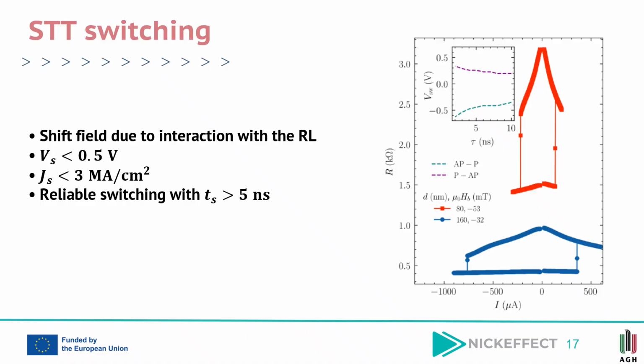In addition, reliable switching operation was achieved for pulse widths longer than approximately 5 nanoseconds, as illustrated in the inset. These results demonstrate that the optimized PT-free cobalt-nickel-based MTJ stacks enable efficient and reliable STT switching at nanoscale dimensions.